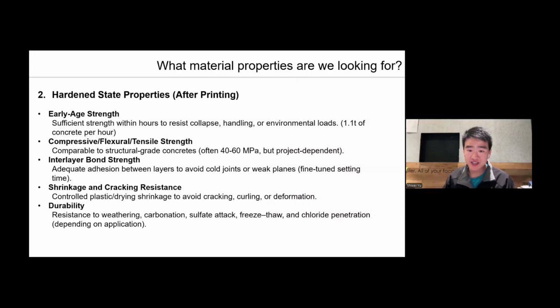Once the printing is done, the next focus is on the hardened property of the material. The first one is the early age strength. The mix must gain enough strength within a few hours to resist collapse, handling and environmental loads. To put this into perspective, on last projects, we might be placing more than 1 ton of concrete every hour. As the structure rises quickly, it also faces significant wind load, so achieving high early strength is very critical for us.